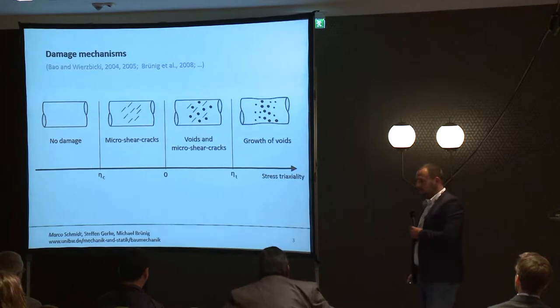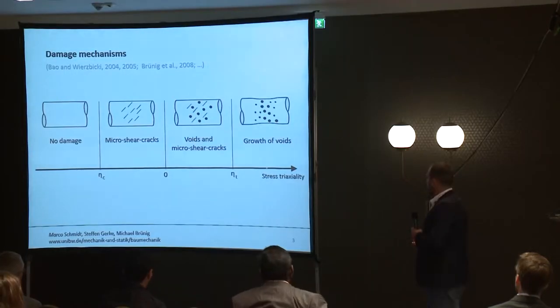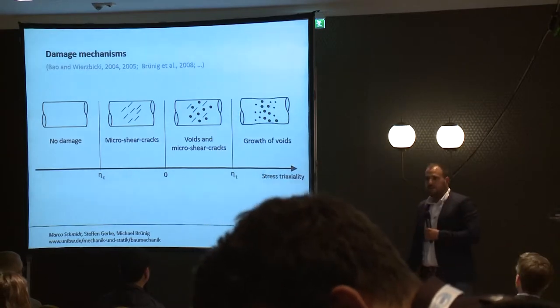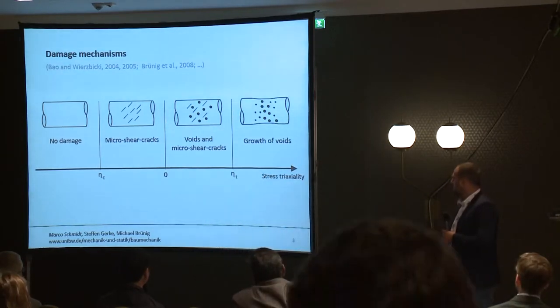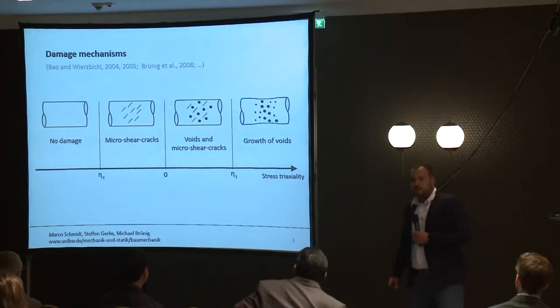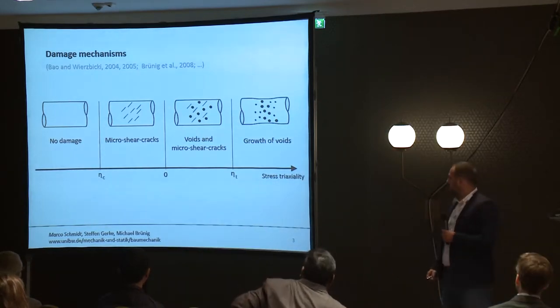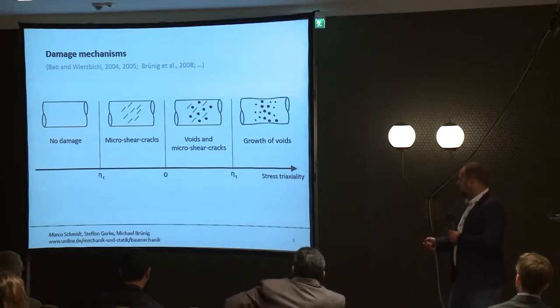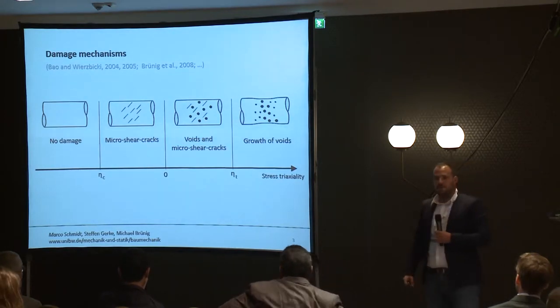There are two damage mechanisms: the growth of voids, which occurs for high positive stress triaxialities, and micro-shear cracks, which occur for moderate negative stress triaxialities. Between these two parts, a mixed form of both damage mechanisms occurs.